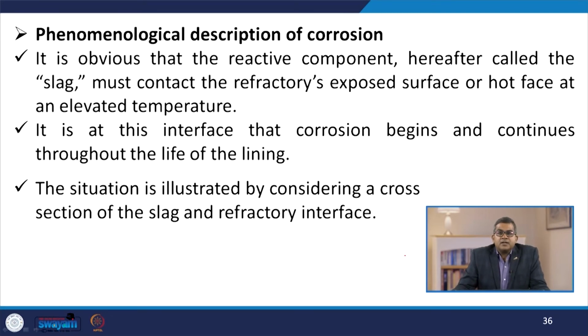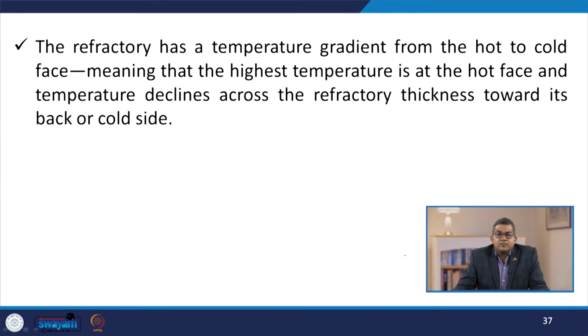Now, it is obvious that the reactive component, hereafter called the slag, must contact the refractory exposed surface or hot face at an elevated temperature. Now, it is at this interface that corrosion begins and continues throughout the life of the lining. Now, we can understand the situation by considering a cross section of the slag and refractory interface. The refractory has a temperature gradient from the hot to cold face, meaning that the highest temperature is at the hot face and the temperature declines across the refractory thickness towards its back or cold side.